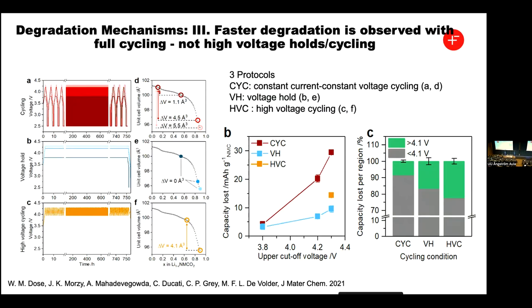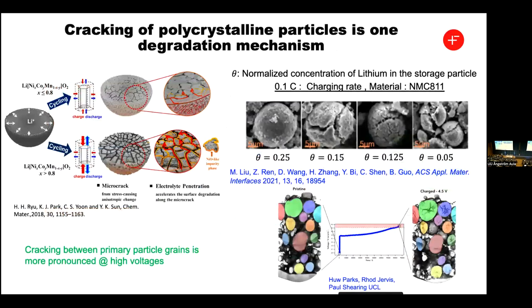So the point of doing this high voltage cycling was to ask the question: if you've got a particle that's expanding and contracting constantly for many, many cycles, does that cause more cracking and more degradation? He kept the time constant between these three experiments, but he showed, surprisingly, that you were going to have much more degradation if you did the full cycling between the lower and upper cutoff voltages, even though you spent less time at high voltages where the degradation process occurred. And so I want to unpick why that might be.